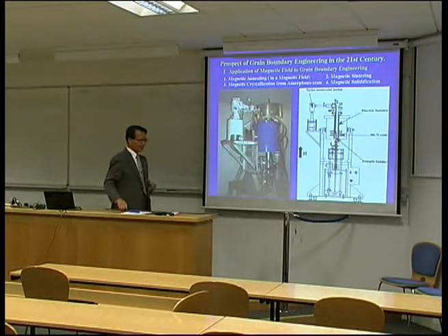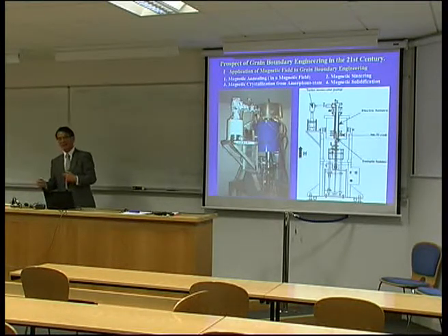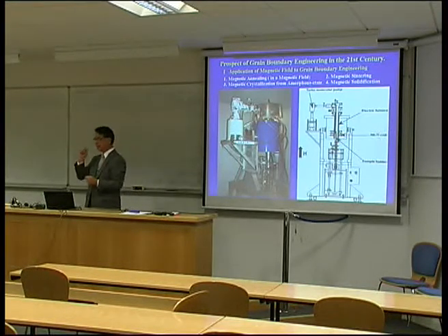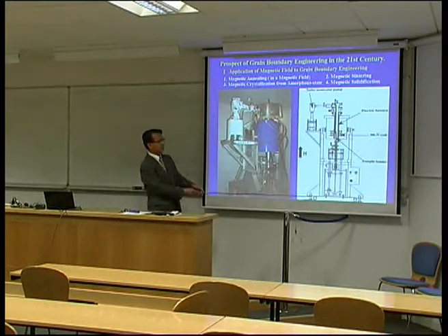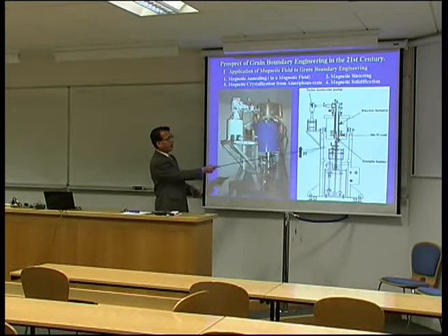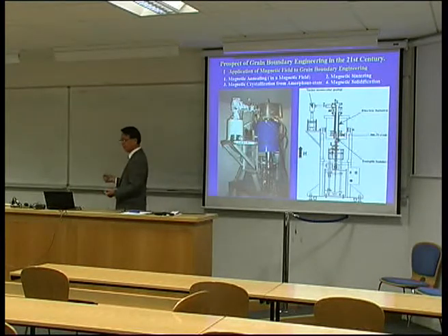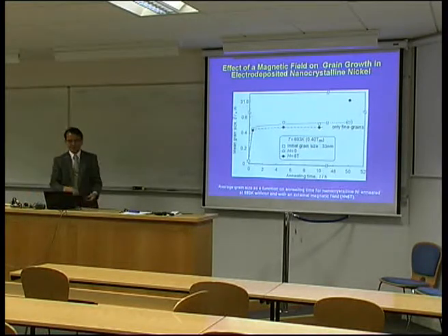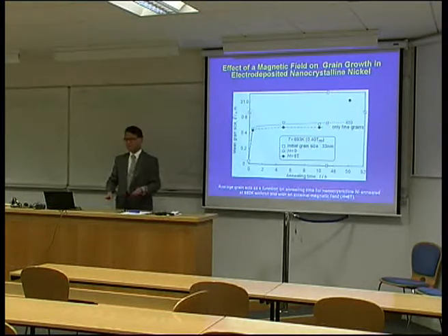Just in the last 10 years, we are using magnetic annealing, magnetic crystallization, magnetic sintering, or any other metallurgical process in a magnetic field, using a superconducting magnet. Our machine heats to a maximum temperature of 1500 degrees with a magnetic field of up to 6 Tesla. Most important, for example, if we anneal nanocrystal material with and without a magnetic field, there